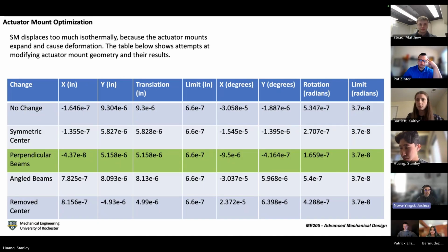The last optimization we did was after we had settled on a final design. The issue we had found is that the two beams in the center that hold up the actuator expand, and that leads to most of the isothermal displacement. We didn't see that in the symmetrical model because we didn't include those two beams, since then it wouldn't be fully radially symmetrical, which is why we didn't see this as an issue until we had a finalized model. The initial model wasn't radially symmetrical, right? The lattice wasn't applied radially symmetrically. We attributed the too-much displacement to the lattice and not the beams. So we did not assume that the beams would be an issue. We assumed the issue lay in the lattice, which was clearly inaccurate.